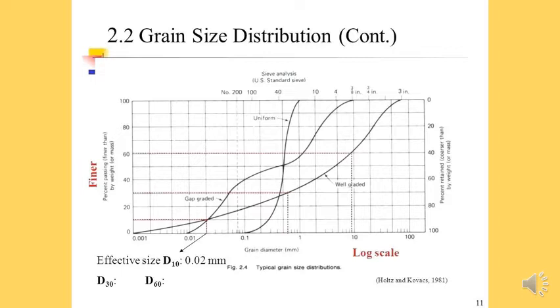30% of the aggregate is smaller than 0.6 millimeters, and 10% of the aggregate is smaller than 0.02 millimeters. So with this well-graded aggregate, in this case there's actually quite a bit of clay and sand inside it.